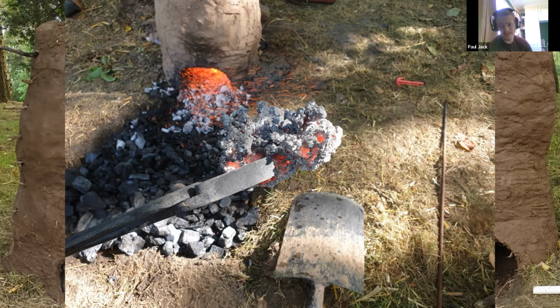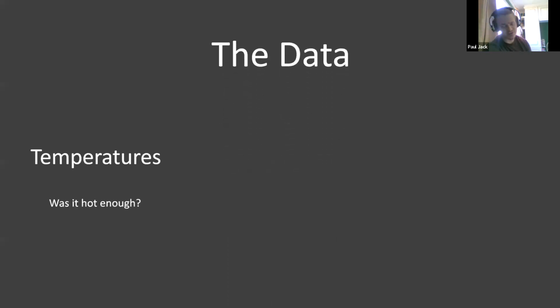We did collect an awful lot of data, and that actually shows us quite a lot of what's been going on within the furnace, and gives us quite powerful insights, and helps us understand the smelts a lot better. So the types of data that we recovered, well, first and foremost, as you might expect, collected temperature data. We collected temperature data from both the smelts, and so this will tell us if the furnaces were actually getting hot enough to produce lots of iron. And it will allow us to as well compare the performance of the two fuels.